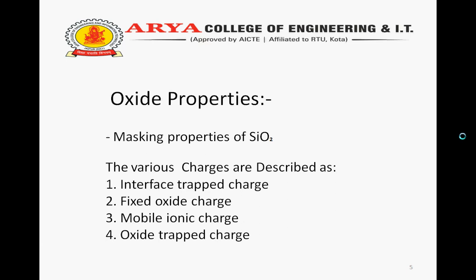The charge results from several sources including structural defects related to the oxidation process, metallic impurities or bond breaking processes. A low temperature hydrogen anneal effectively neutralizes interface trapped charge. The density of the charge is usually expressed in terms of unit area and energy in the silicon band gap.